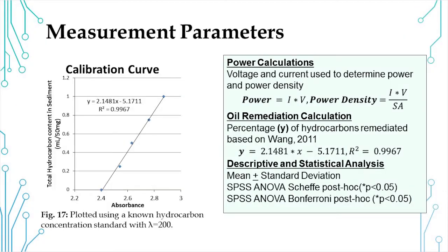We measured the electrical output of voltage and current over a 10K resistor over a 10-day period for both systems. For the SOM system, we also analyzed the oil remediation process by extracting the hydrocarbons and then using UV-vis spectroscopy to measure the absorbance. For our data, we calculated the power and power density using projected surface area to study how much power is produced per unit of material.